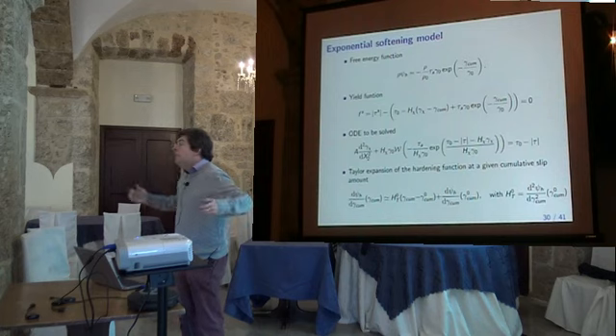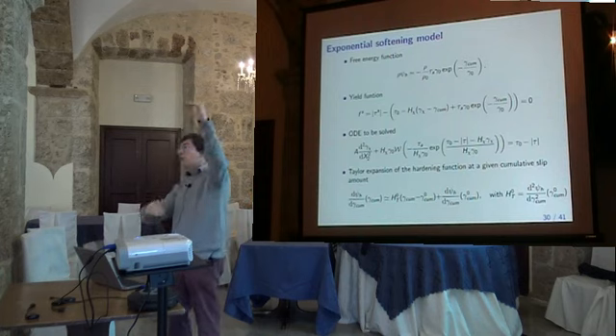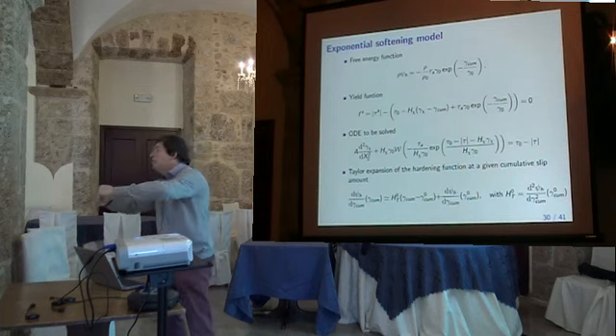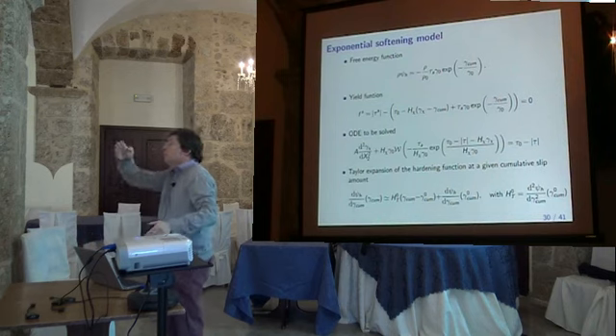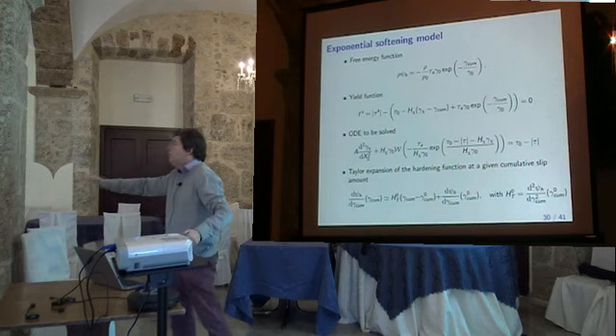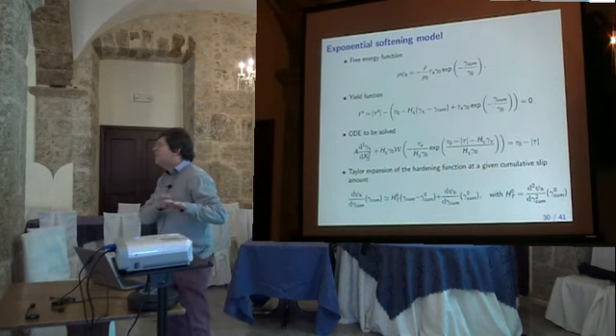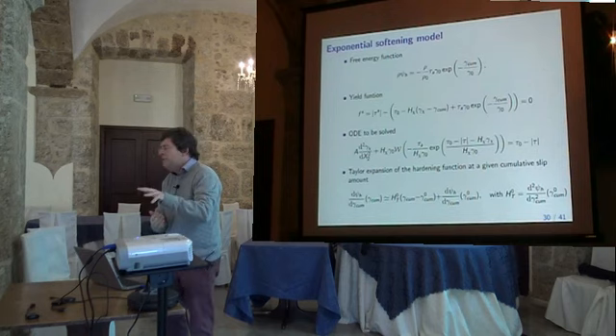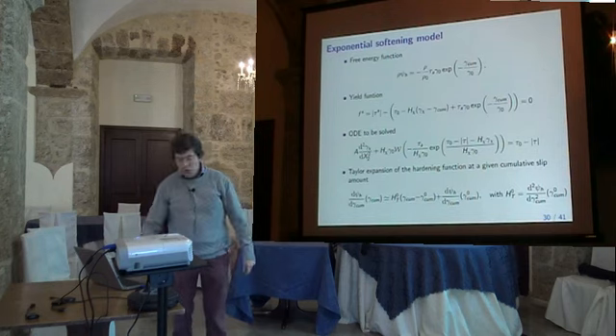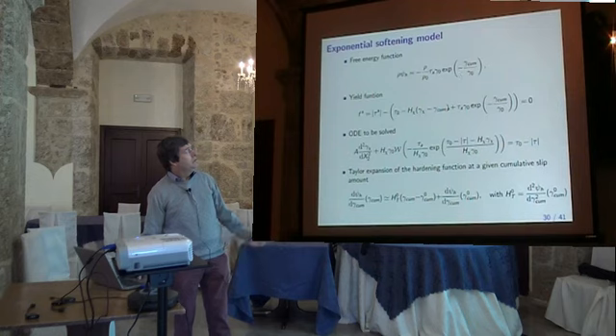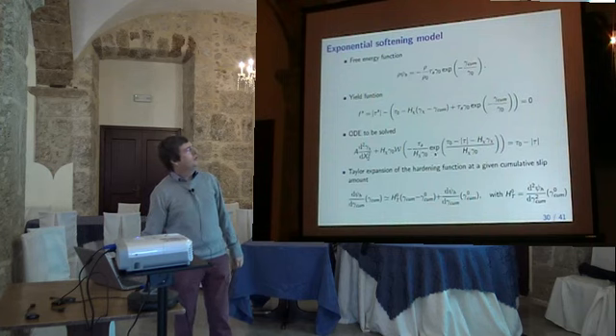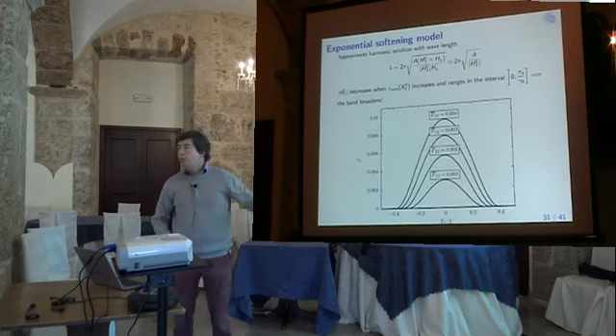I mean, if you want to simulate 100% and you have a slope with localization, very soon you will have a problem with your model if you don't try to make saturation. I'm not interested in fracture, I want simply to have plasticity. So we do some exponential function, we try to solve it. So Jean-Michel has found a way to solve this, at least approximately. So I don't go into the details of this solution, but this is the result.